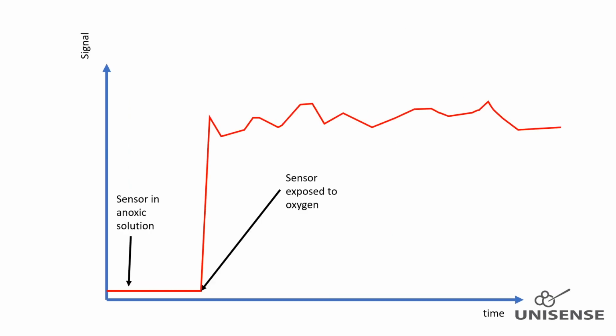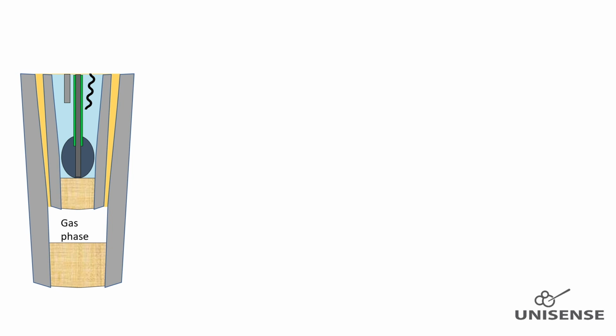If the sensor is sensitive to oxygen and it is for sure not physically damaged, potentially it could be due to a gas phase in the front guard tip, which will cause oxygen to diffuse to the nitrous oxide sensor tip membrane. Such gas phase can easily be removed by inserting the tip into degassed water, which will drag the gas out of the tip through the membrane.